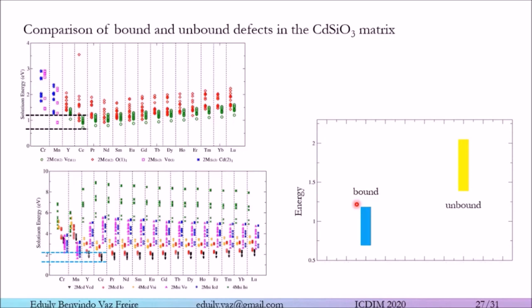Well, to finish the results, I will now present the comparison between the bound and unbound defects in the CdSiO3 matrix at 0 Kelvin. Here, for the bound defects, we have a much lower energy than in the unbound defects. And more, all the bound defects for rare earths have less energy than the lowest energy for unbound defects. Okay?